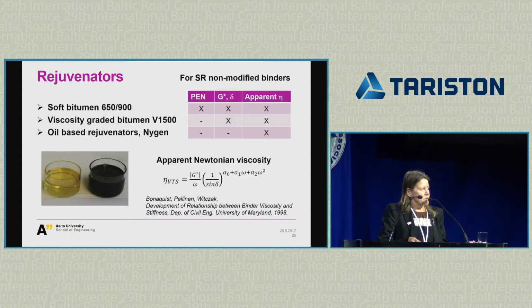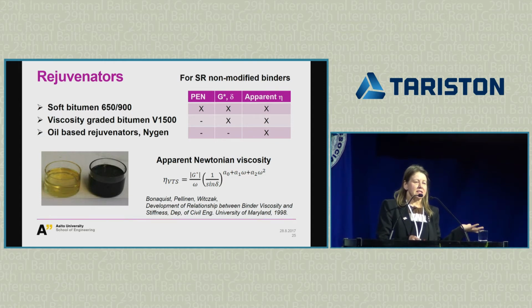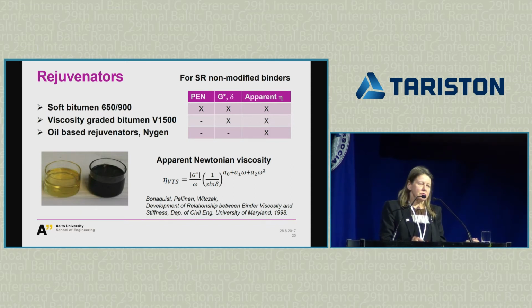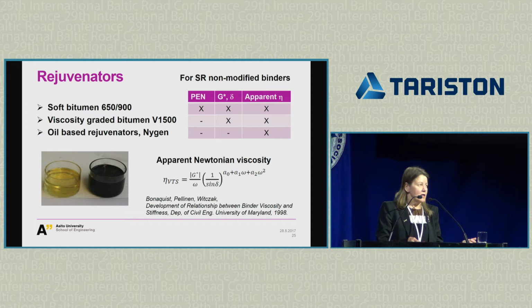So there comes a little bit of a problem if you think about the alternatives for rejuvenation, and this is now what I'm talking about, is really hot in place recycling. So we can use soft bitumen, this is very typical. Then we have been doing some trials for softer bitumens, and Mihalina Makowska will tell you more tomorrow about these trials. And then you can use these oil-based rejuvenators. As you can see, only viscosity could be measured in all of those.